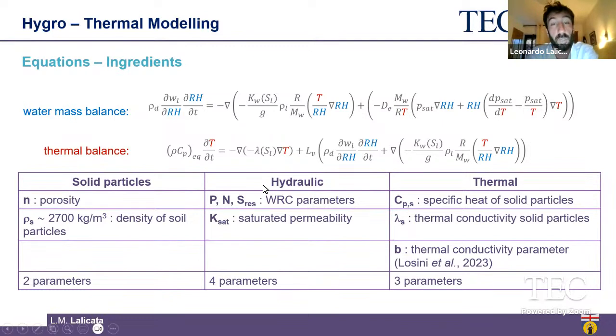Then we have four parameters for the hydraulic part, and three of them are the water retention parameters, for instance, that are the same ones that describe the evolution of the liquid permeability with the degree of saturation. In addition to that, we need to evaluate the saturated permeability, K-SAT, and this can be done with a very standard and traditional oedometric test in a geotechnical lab.